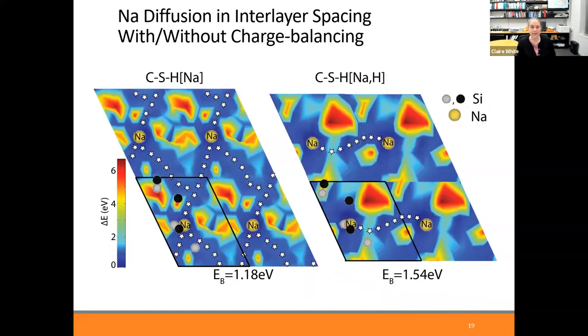The last thing I'm going to talk about for this part of the research is how easy it is for either calcium or sodium to move in the interlayer region of the structure, which is that hydrated region. We did these calculations whereby we can calculate the barrier to diffusion. Can the atom easily diffuse around, which would be an indication that that element can easily leach out of the system, for example, or is it kind of stuck quite well in its location and it can only diffuse in the local vicinity of where it originally sits?